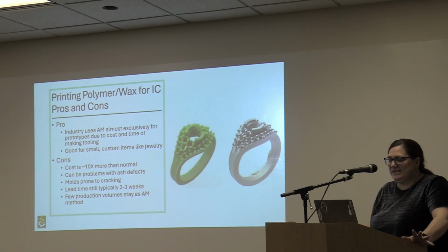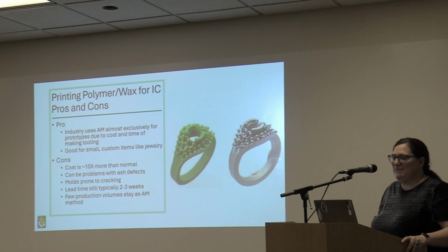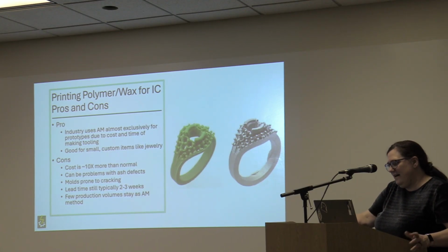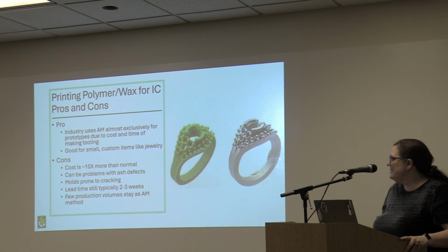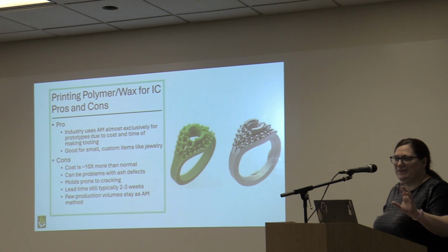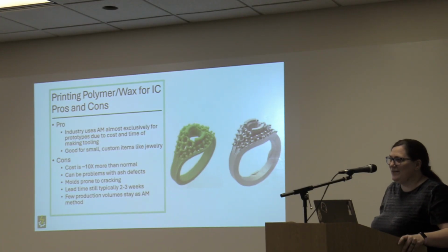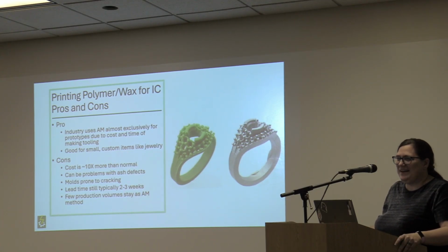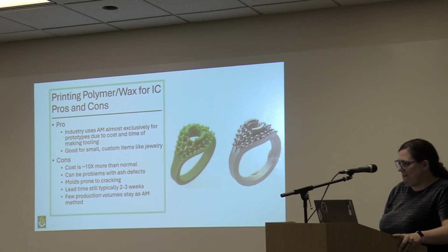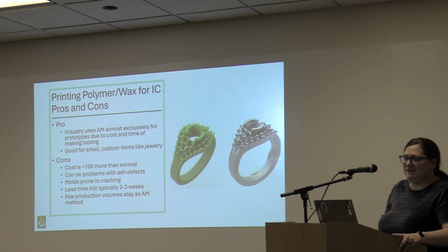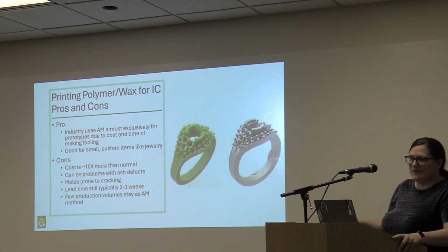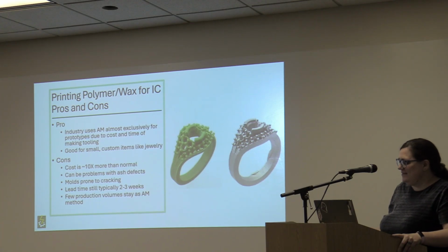It's also a very good process for very small things. Actually, if people come to us with inquiries, if they're very tiny parts, we will just direct them to one of the other additive investment casting people. They also have issues when they do print like this with ash getting caught inside of the mold, which causes metal defects. They have problems with the molds cracking due to the thermal expansion of the print when they try to burn it out. There's all kinds of challenges in these areas, even when they are being used. But due to the cost, that tends to be a recurring theme. And typically, if it's not a custom low volume thing, at some point they will switch to tooled standard lost wax.